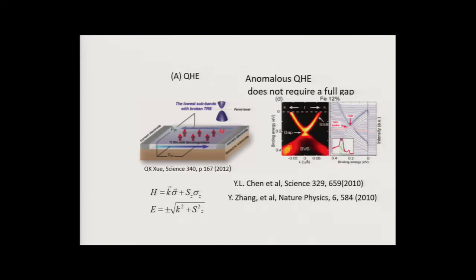So for those of you who know, the story was that if you have a topological insulator and you have a Dirac state on the surface of it, when you put in magnetic impurities, what you can think about is that this Hamiltonian, in the case of magnetic impurities which are ferromagnetically ordered out of plane, is essentially a spin in a magnetic field whose component has a kx, ky, and a z component. So without this term with sigma z, this would lead to a nice Dirac cone on the surface states, and those are well established in the case of the pristine topological insulators. But then with magnetic order, it was argued that it will open a gap. And you can see that the gap opens up in the presence of the ferromagnetically ordered impurities on the surface of the topological insulator.